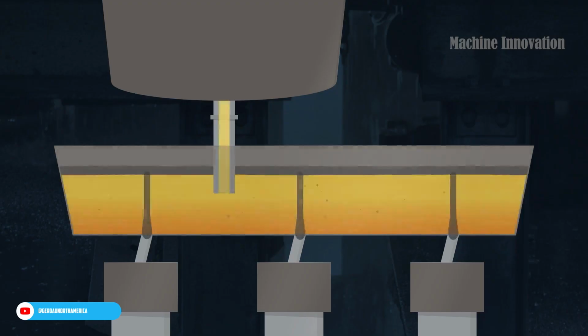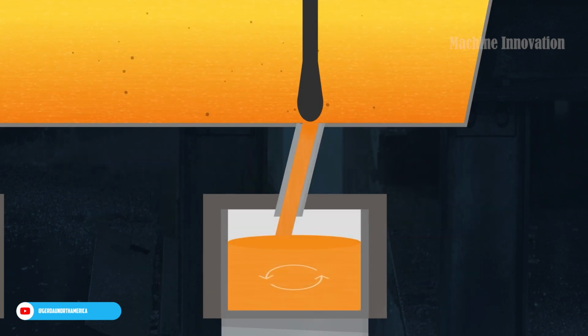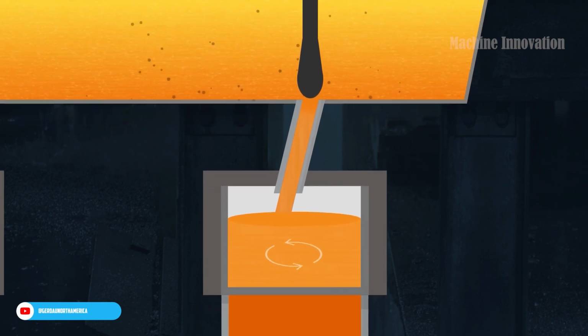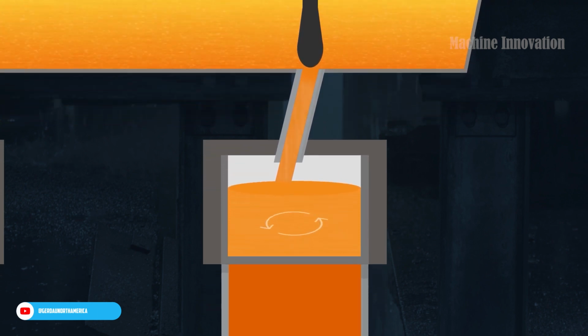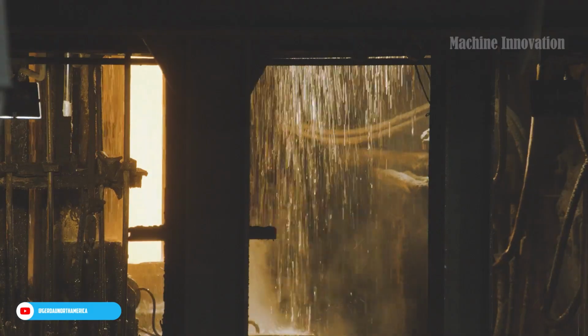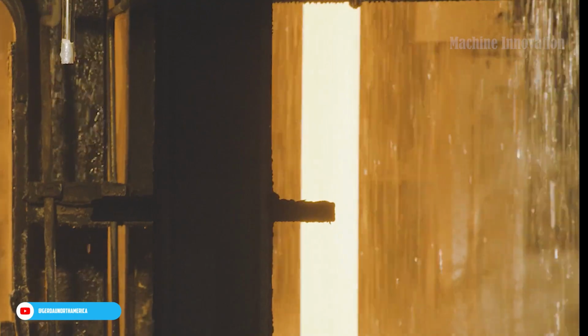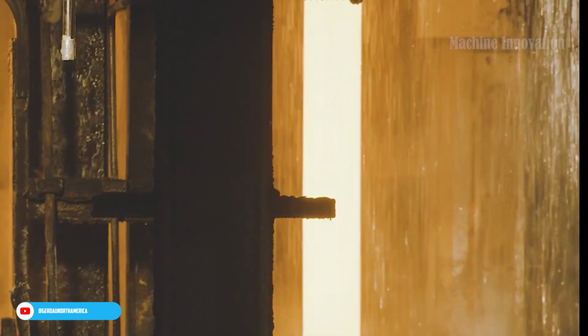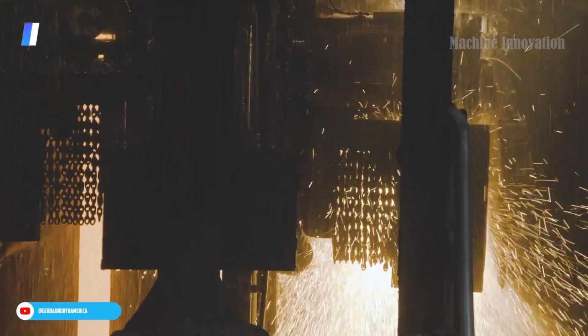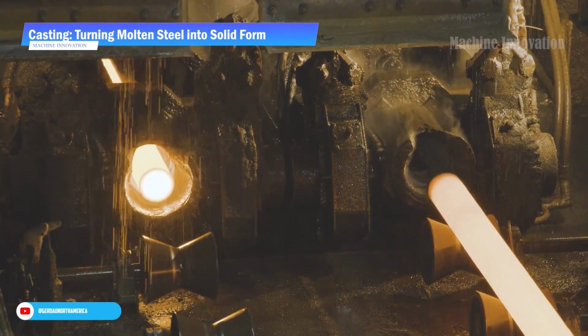To further refine the steel, Gerdau employs vacuum degassing, a process that removes undesirable gases like hydrogen and nitrogen. By applying a vacuum to the molten steel, these gases diffuse out and are absorbed into the surrounding fluxes, which helps prevent internal defects in the final product. This process is particularly important for applications that require extremely durable steel, as excess hydrogen or nitrogen can lead to brittleness. After refining, the steel is ready for casting.